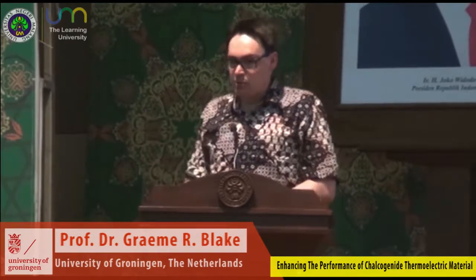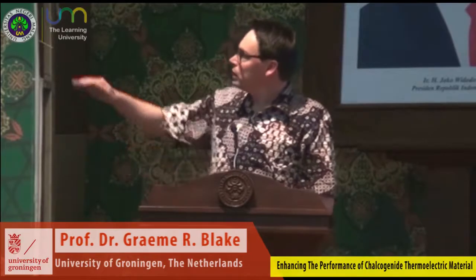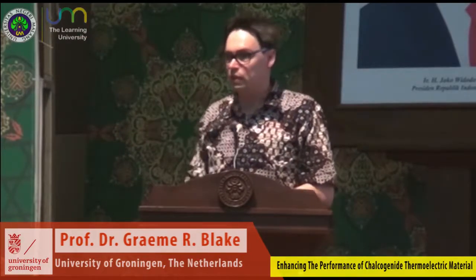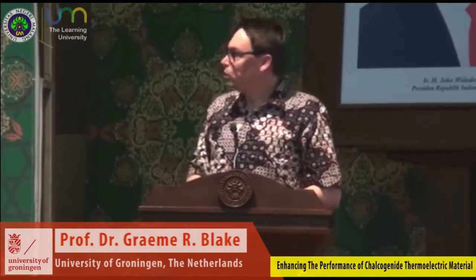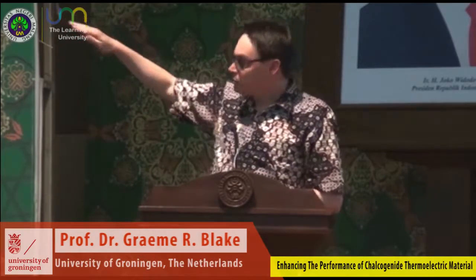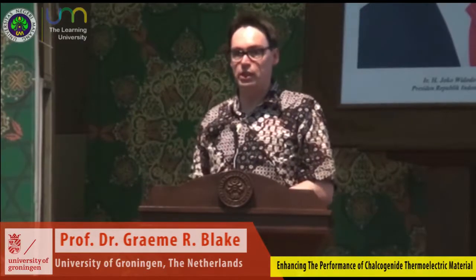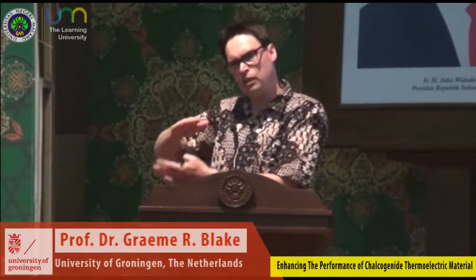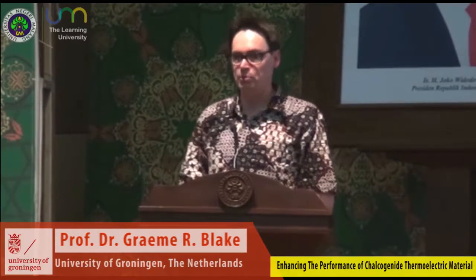And this is a similar material that we've made in our lab. It's a new material containing rhodium. And again, it has a similar triangular lattice of the transition metal rhodium oxide. And sandwiched in between the rhodium oxide layers are in this case barium oxide layers, which don't exactly match. So again you have a mismatch of lattices and disorder and good thermoelectric properties.